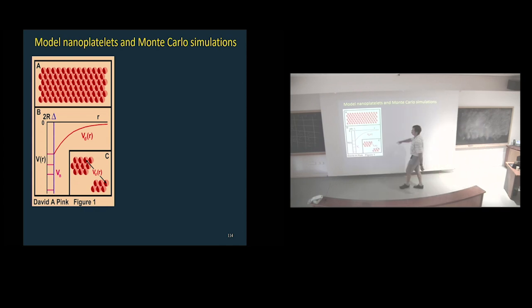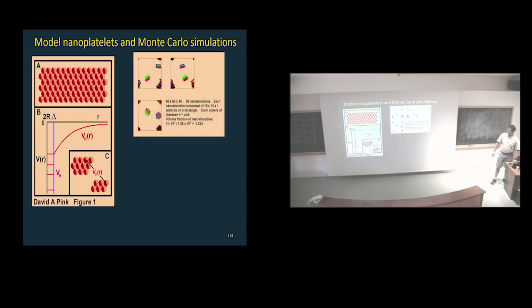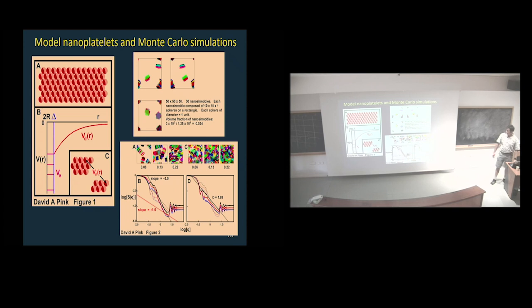So what he did is he created spheres interacting via van der Waals forces. Then the interactions are all the same, by the way. And then he did just Monte Carlo simulations. And he obtained different microstructures. And what did he do? He just calculated the structure factors from those things, the relative position of each little ball that makes up the platelets relative to each little ball. It's a big summation. And then he predicted certain slopes.